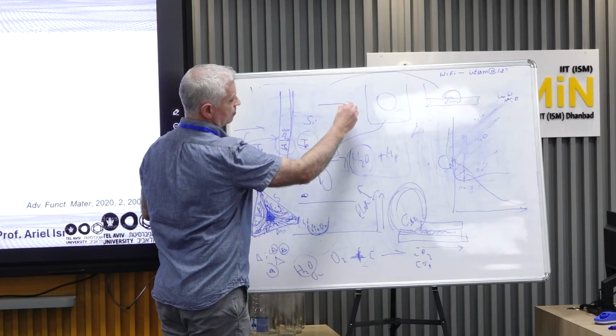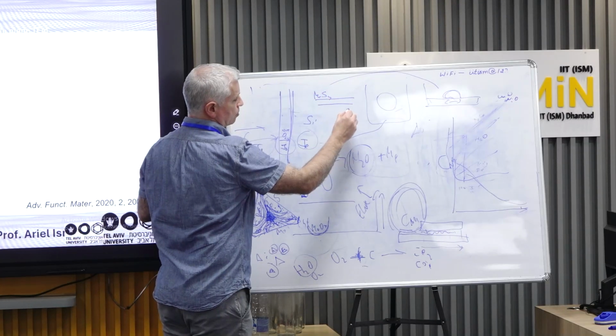Okay, so the same for molybdenum or tungsten disulfide in this case. You have the molybdenum that reacts with the sulfur, right, to lead to MoS2. So you have a layer of MoS2, and then the metal, molybdenum or tungsten. But then the sulfur needs to diffuse here.